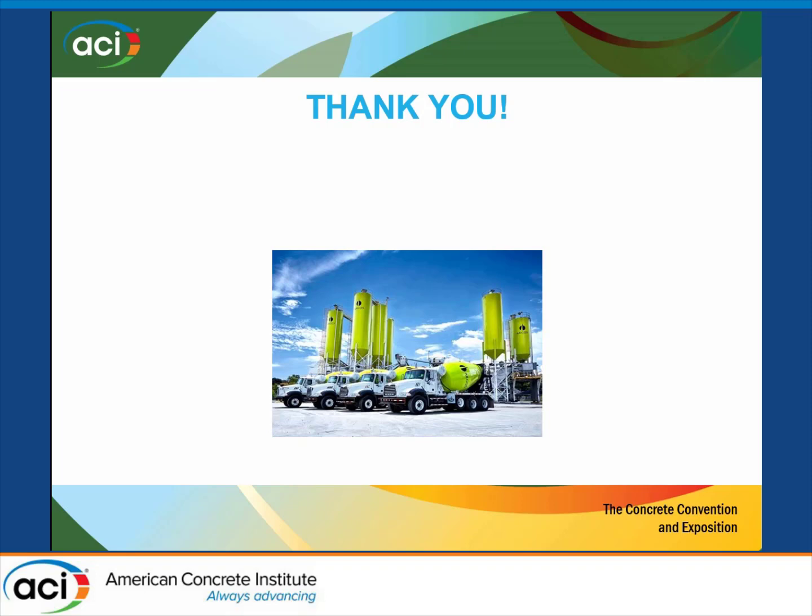Audience member from Belgium: We had the same basic behavior. Now the contractor, instead of ordering S3 — about a 6-inch slump — they order S4, because that's the concrete they actually need. The concrete producer now sets the right concrete at the right price — it's a higher price — but the contractor knows it's better for them because they don't spoil it by adding water. This experience proves you educate people with these systems, because I fully agree: they don't know what slump is. They think a 4-inch slump looks like a low slump, and that's why they order too low.